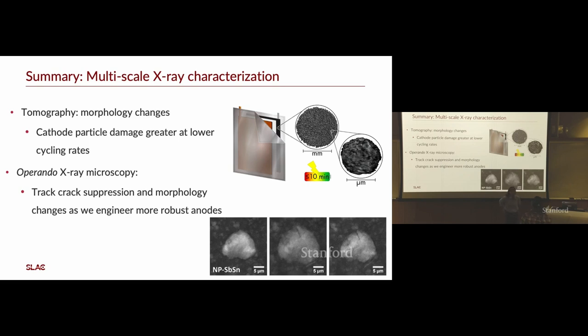So the SEI layer, the solid electrolyte interphase, is on the nanometer size, and it is made up of materials that are very close in chemistry to the electrolyte. Because we're doing this in situ, it is impossible, I would say, to see this SEI layer, because the X-rays look at electron density, and the electron density is identical to the electrolyte. And so it is very low in contrast, and so it's not visible. So when you're picking out a tool, you really need to think about what you want to study and pick the right tool for that.